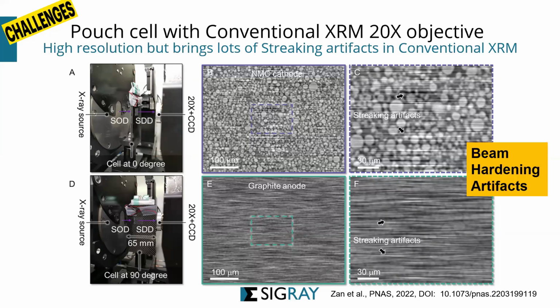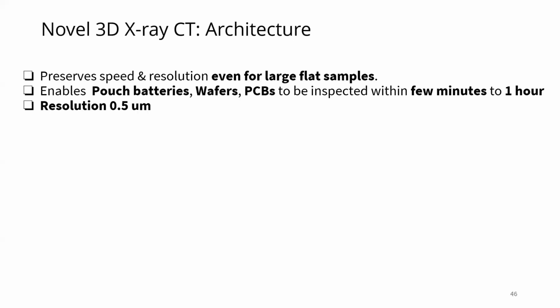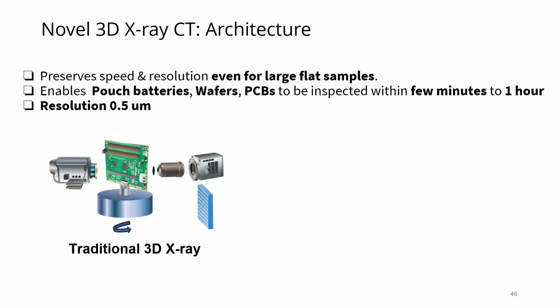So this is due to what you call beam hardening effects that those who are doing X-ray microscopy or micro-CT will be very familiar with. Next, to solve this problem, we designed a novel tool that can work with large samples, therefore pouch batteries or wafers or PCBs can be inspected very fast, from a few minutes to an hour, with a resolution down to half a micron.